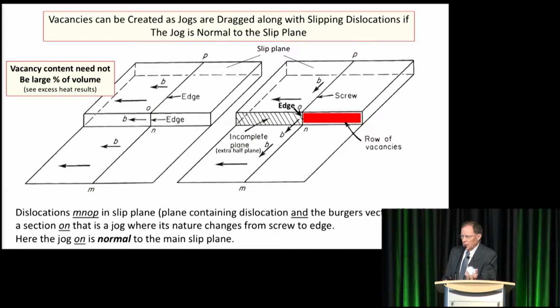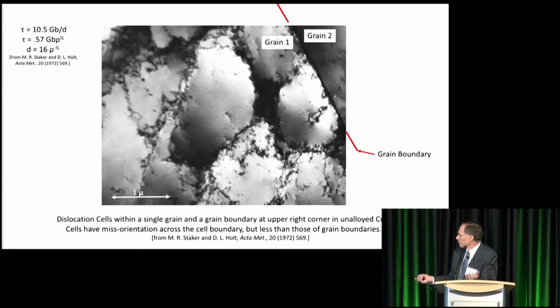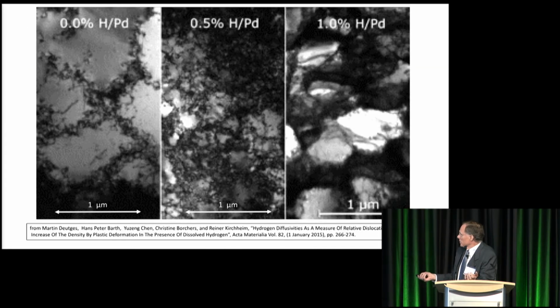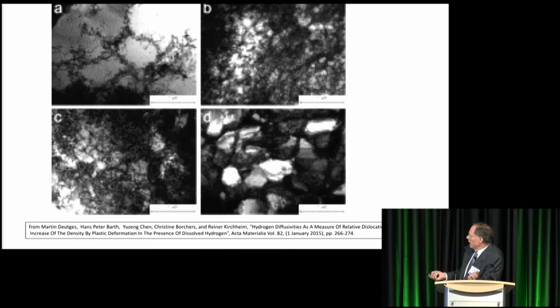However, as you'll see at the end of this experimental method, and this has also been calculated by others, the volume percent of the nuclear active area is very low. So this mechanism would be adequate to supply the volume needed. These are the dislocation structures, the black lines, and in unalloyed palladium, it forms cells as it does in all the other FCC structures. And in the hydrides themselves, these dislocation densities are very high, as well as